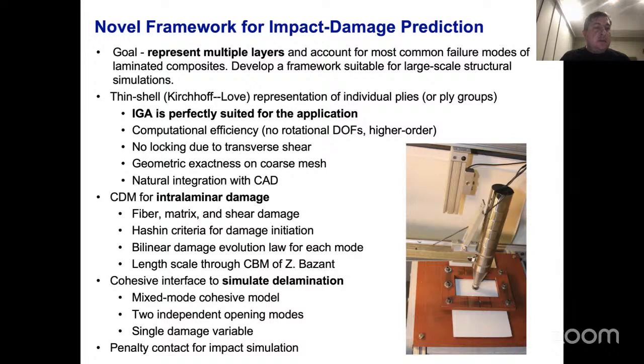And so the idea is to use the Kirchhoff-Love theory to represent individual plies, or ply groups. The individual plies are truly thin. There is really no need to introduce transverse shear strains. There are no transverse shear stresses. We feel isogeometric methods are perfectly suited for this application because the definition of structural surfaces can be obtained directly from CAD. You get the computational efficiency because you only get displacement degrees of freedom on each individual ply. No rotational degrees of freedom, no possibility of transverse shear locking because there is no transverse shear. You get geometric exactness on the coarse mesh and a natural integration with the CAD systems.